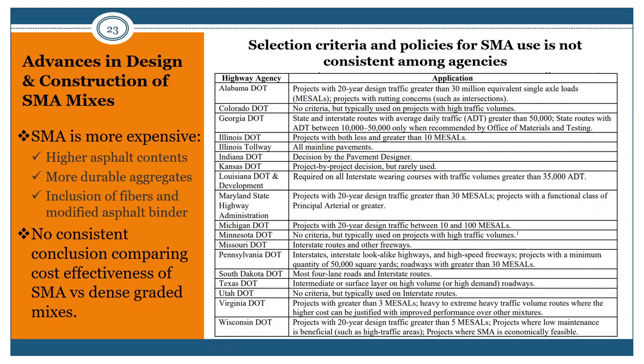SMA certainly is more expensive, simply because of the higher asphalt contents, the more durable aggregate requirements, and the inclusion of fibers and modified asphalt binder. From different agencies, there is no consistent conclusion comparing cost effectiveness of SMA versus dense graded mixes. However, many agencies, but not all, have found SMA mixtures to be cost effective as compared to conventional dense graded mixes. The cost effectiveness issue will be discussed in greater detail in a later part of this presentation.